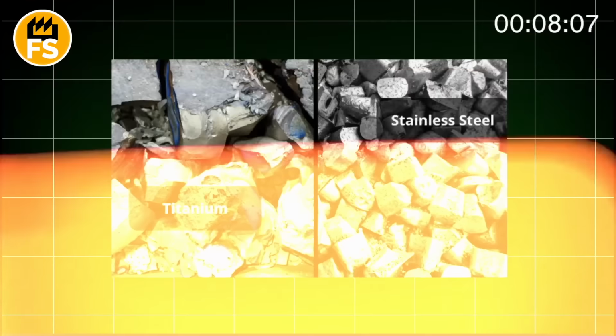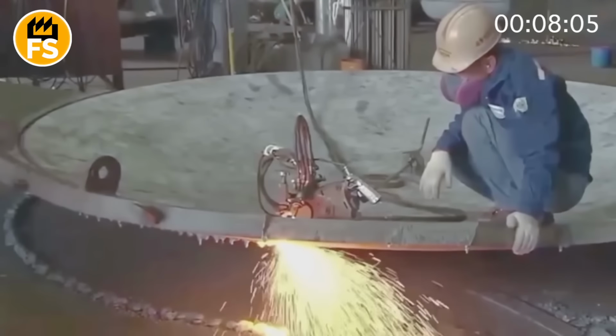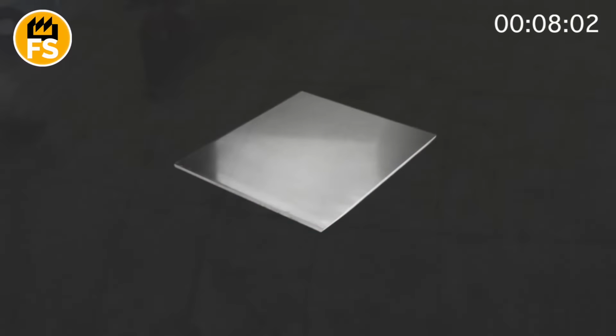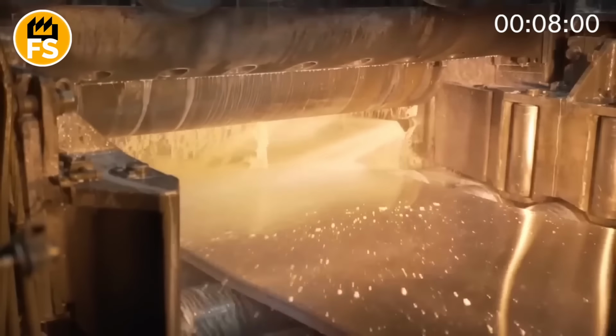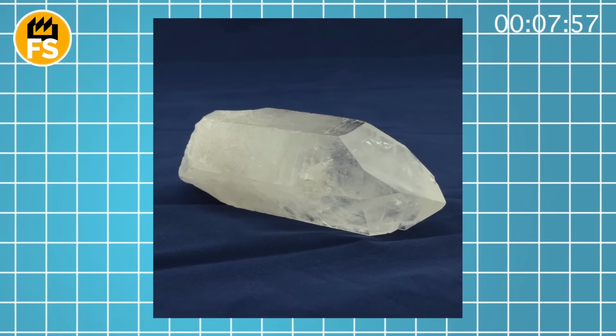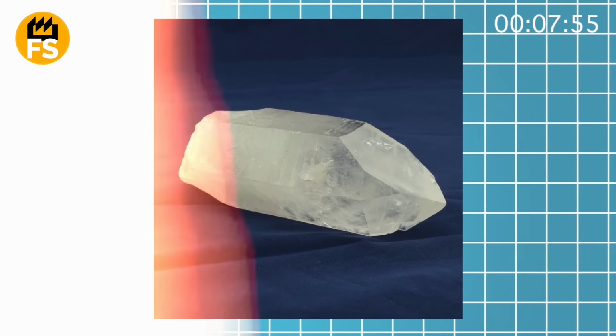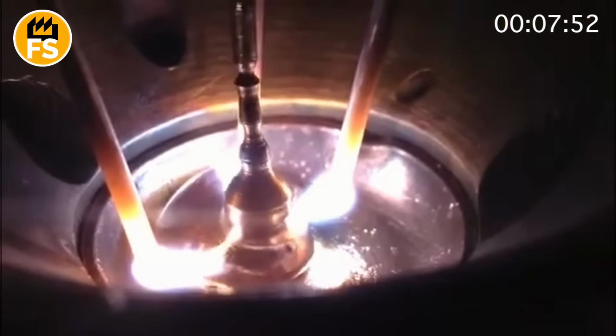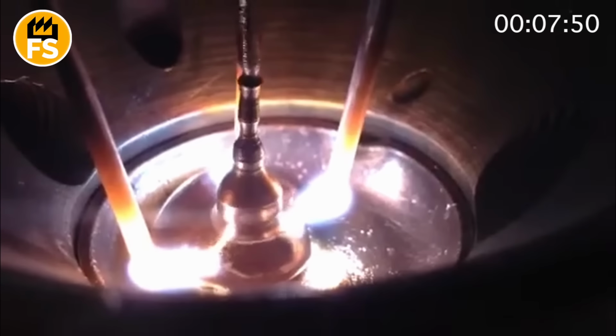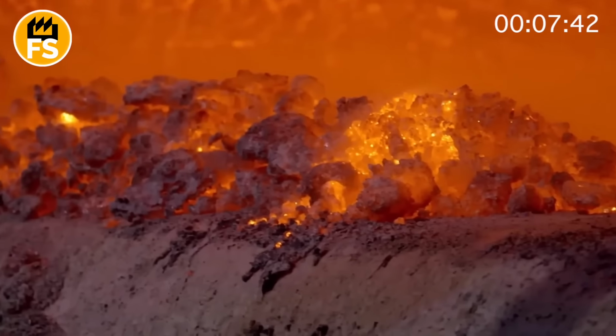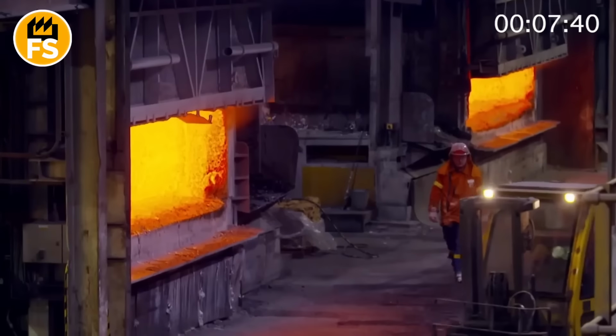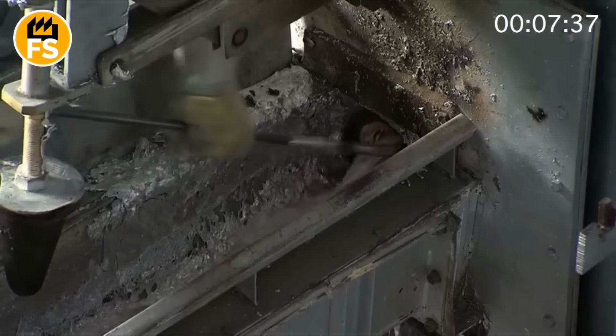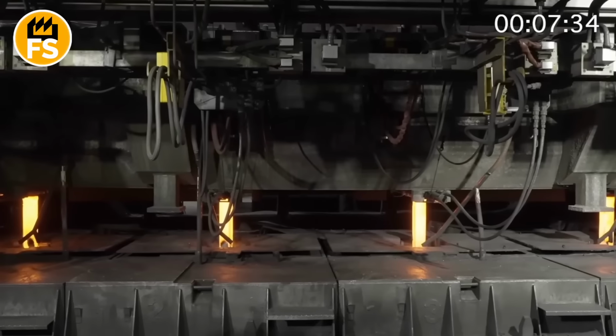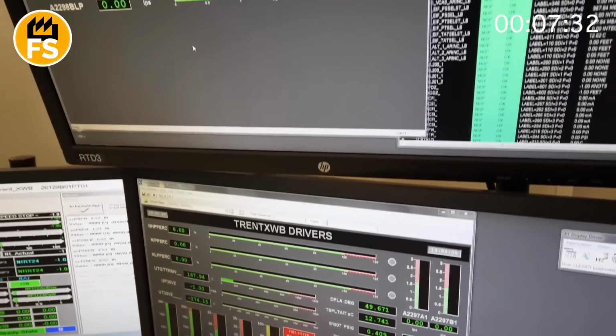Steel is more cost-effective and easier to manufacture, as it can endure high pressure and impacts. Titanium, on the other hand, offers superior strength, corrosion resistance, and non-magnetic properties, which reduce the risk of detection. However, titanium is more challenging to process and weld, as its melting point is significantly higher, approximately 3,034 degrees Fahrenheit compared to steel's 2,500 degrees Fahrenheit. Before construction begins, all metal sheets undergo heat treatment, which involves heating, cooling, and applying special anti-corrosion coatings.